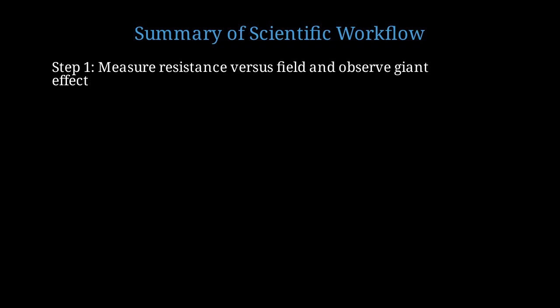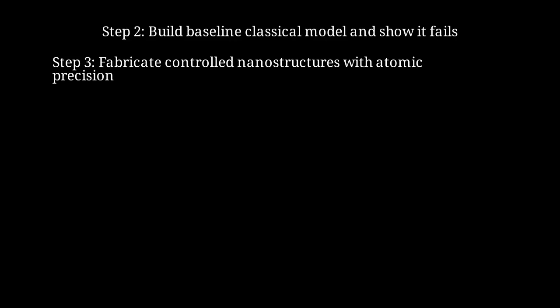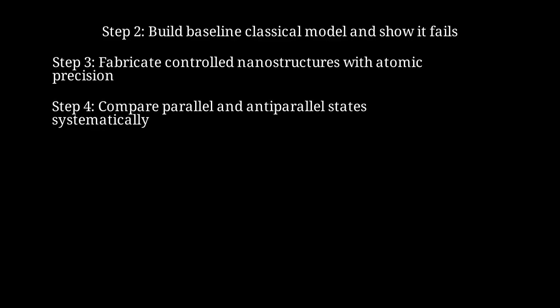Let me summarize the scientific workflow we've followed in this lecture. Step 1. Measure resistance as a function of magnetic field and observe the giant magnetoresistance effect that cannot be explained by classical physics. Step 2. Build a baseline classical model without spin-dependent scattering and show that it predicts no magnetoresistance, revealing the inadequacy of the classical picture. Step 3. Use modern thin film deposition to fabricate controlled multilayer nanostructures with atomic precision. Step 4. Systematically measure and compare resistance in parallel versus antiparallel magnetic configurations to quantify the effect.